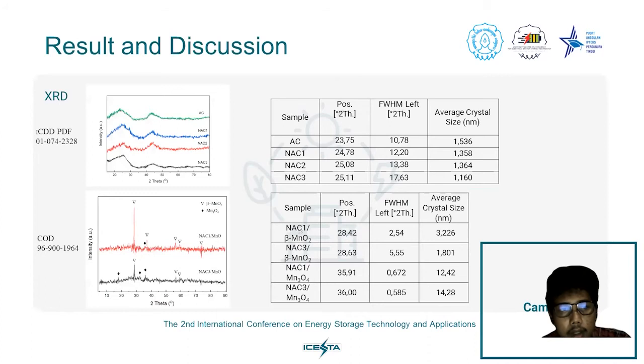Then for the result, you can see here the XRD result, from the activated carbon to nitrogen activated carbon composition 3, you can see that the peak of carbon is shifted to the right. It means that the nitrogen in the carbon succeeded to dope into the activated carbon. And then you can see the crystal size here.